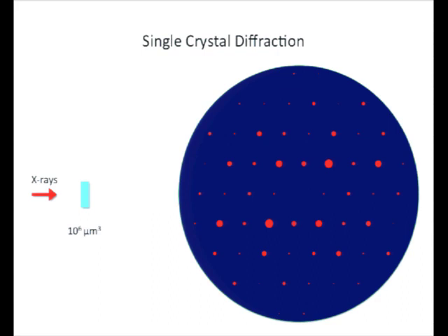And now a quick crystallography lesson. Those intensities are proportional to the square of what we call the structure factor. The structure factor is simply a summation over all the atoms in your unit cell. So n atoms in the unit cell, they have some scattering power, which has to do with the number of electrons for the case of X-rays, and they are somewhere in the unit cell. They have coordinates. All the structural information is there in this structure factor.